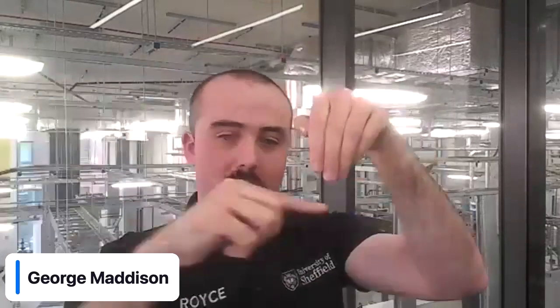But the process fundamentally is you have a feedstock and you have an energy source, and the feedstock passes in front of the energy source, and this energy source moves around with the feedstock, and you deposit a structure like a giant weld bead, effectively. And if it's wire-fed, it's usually called wire arc additive manufacturing. And if it's powder-based, it's usually with a laser, and it's called blown powder directed energy deposition.